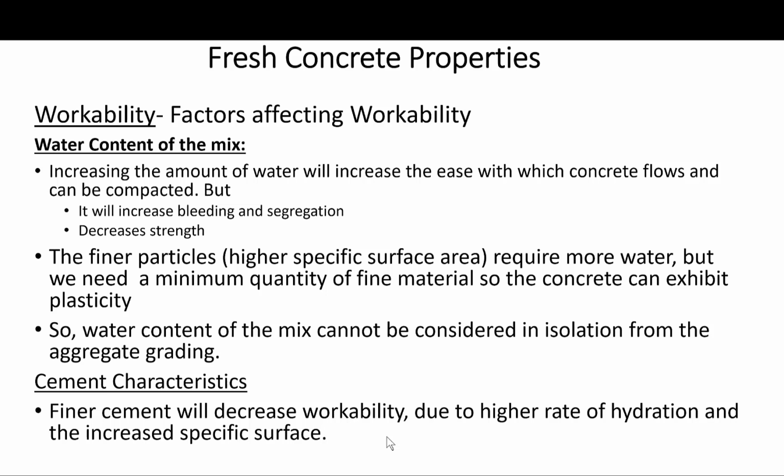Remember when we talked about the cements? So it has been found that if cement is delivered to the job hot, let's say above 100 degrees Celsius, there may be a considerable loss of workability due to more rapid hydration and evaporation of water. In addition, at temperatures higher than 60 to 80, flash set may occur. So be careful of that.